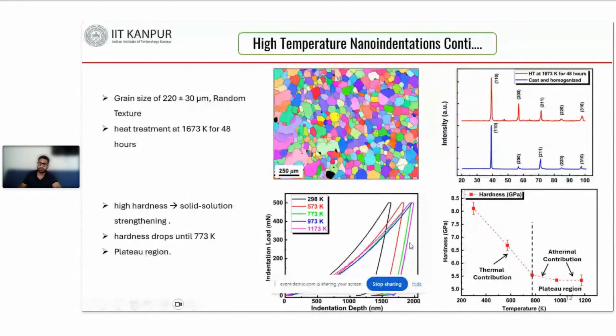To understand the deformation behavior, we plotted the hardness as a function of temperature, and you can see here the hardness is pretty high. This can be a result of solid solution strengthening of this material, because it has 5 principal elements and was developed by the high entropy alloy concept. So the movement of dislocations will be difficult in this alloy, and that way it has a very high solid solution strengthening.